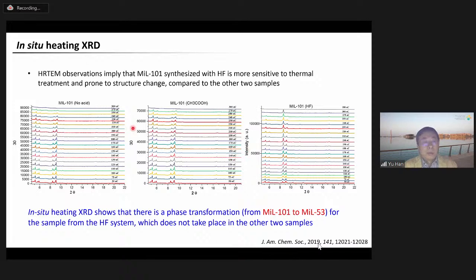So to verify this speculation, we conducted an in situ heating XRD experiment, and the result confirms that the sample synthesized with HF is more sensitive to thermal treatment and prone to structure change as compared to the other two samples. And we observe a phase transformation from MIL-101 to MIL-53 for this sample, starting at about 120 degrees. This phase transformation doesn't take place in the other two systems.